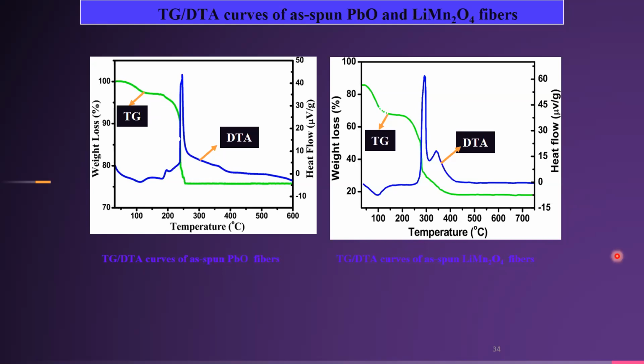In the second stage, a weight loss of 22.40% in the temperature range of 100 to 260 degrees centigrade is maybe due to the decomposition of nitrates and PVA main chains existing in the as-spun sample, and a corresponding broad exothermic peak is observed in the DTA curve. There is no weight loss observed in the TG curve in the temperature range of 260 to 600 degrees centigrade, which indicates the complete decomposition of organic derivatives from the as-spun sample to form the beta phase oxide. Similarly for the lithium manganese oxide nanofiber sample, we can see the same.